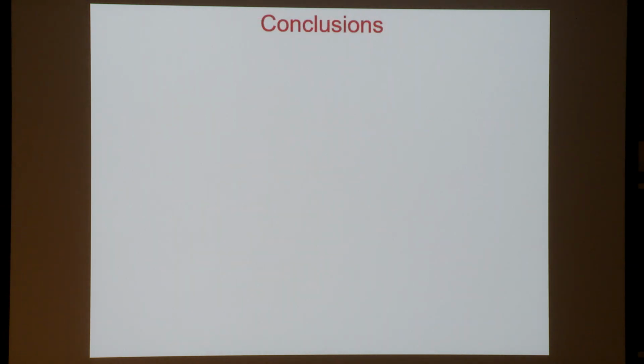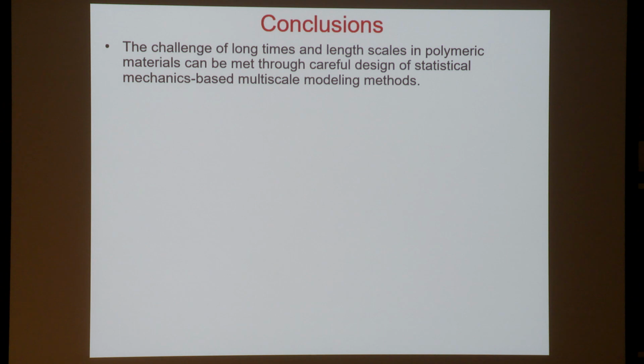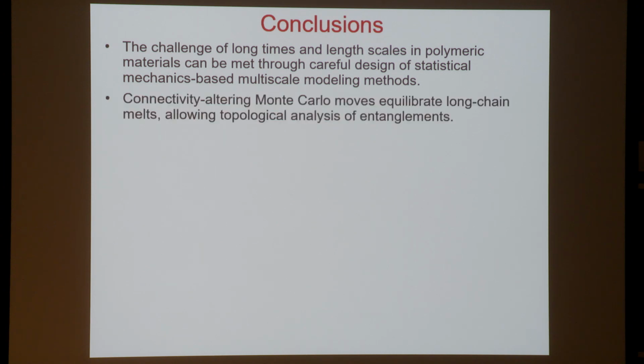So to leave you with some conclusions, there is a tremendous challenge associated with long times and length scales in polymeric materials, and this can be met through the design of carefully planned statistical mechanics-based multi-scale modeling methods. We have seen that connectivity altering Monte Carlo is quite useful for fully equilibrating melts of large molecular weights at all length scales, and also conducting topological analyses in order to learn about the density of entanglements in these melts.